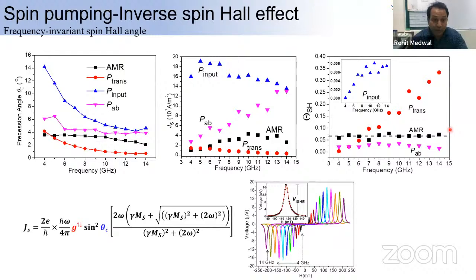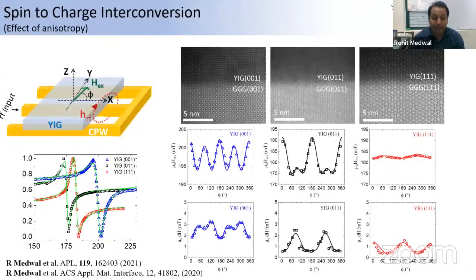And then, how can we improve this pumped spin current into the platinum? Can we control this pumped spin current into the platinum? That was another challenge we were trying to consider. So for this, we designed a special material, which is yttrium iron garnet, which we call YIG. I tried to control the anisotropy of this YIG by growing it epitaxially in different directions. So we grew these YIGs on 001, 011, and 111 orientations of the substrates.